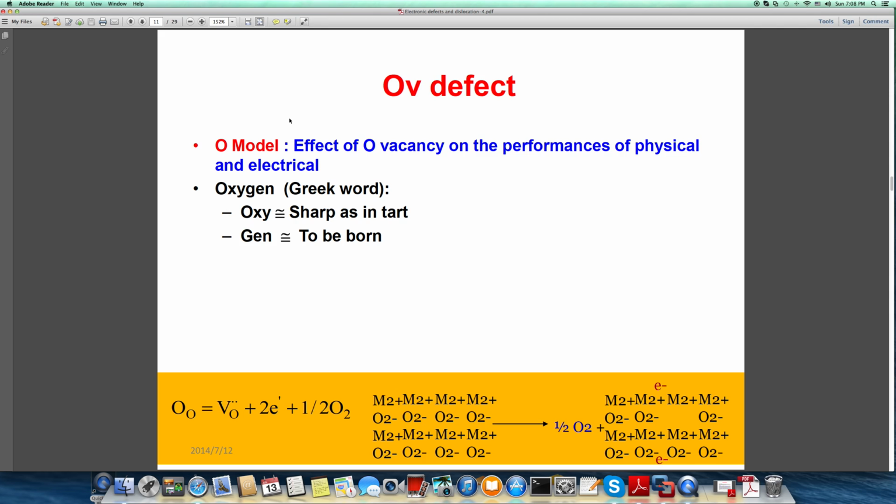and then we can further dive into the oxygen vacancy after we understand the oxidation reaction and the material interaction. So let's deep dive into the oxygen vacancy here. Basically we study the oxygen vacancy, which can be described by this equation. For oxygen occupying the oxygen site, we can describe it as O_O here. When the oxygen is gone, it leaves the oxygen vacancy there. Here is an example: oxygen is gone, and the vacancy site is generated. Because this oxygen has 2 electrons outside, we also release 2 free electrons. You can see the vacancy generation and the 2 free electrons are also created.